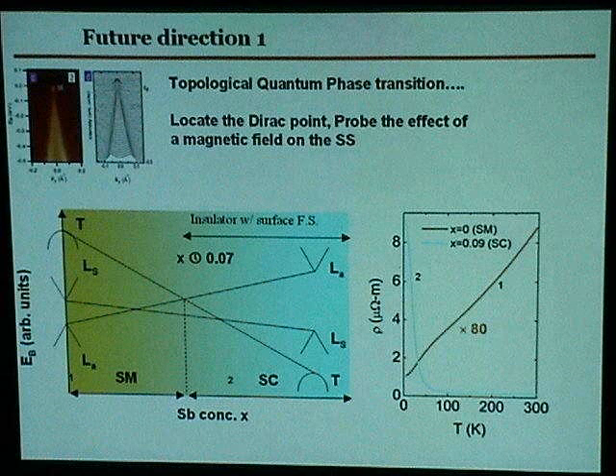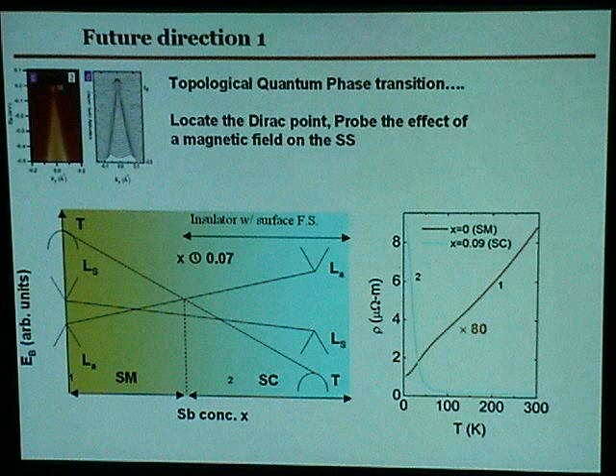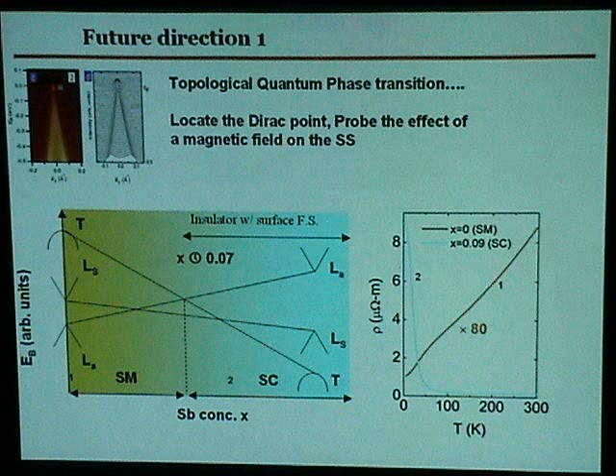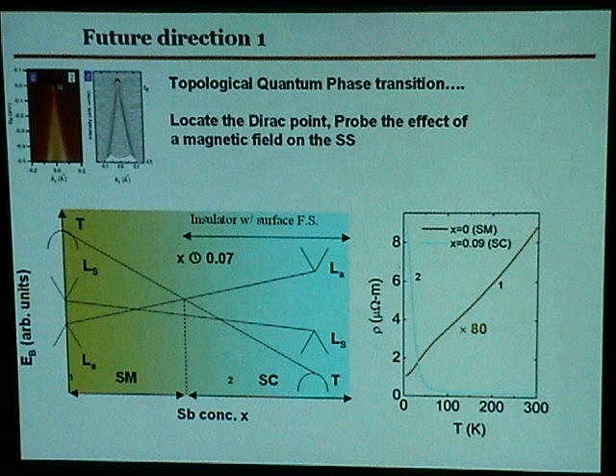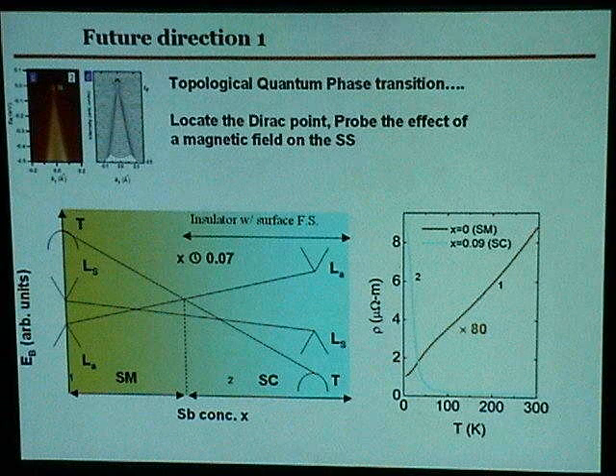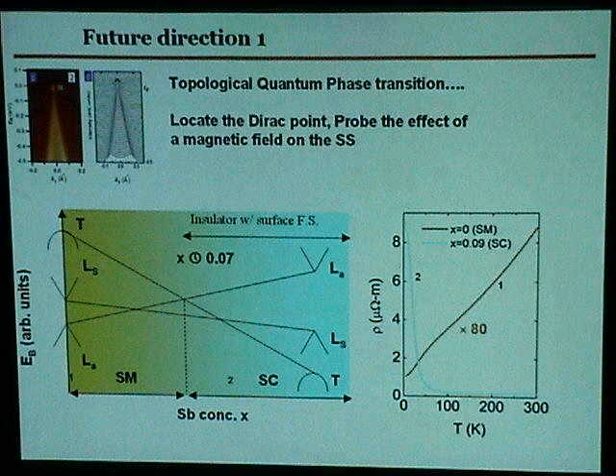You can get rid of other surface state contributions by changing the bulk volume to surface area ratio — just look at the scaling. We are already trying to do this: look at samples and do transport measurements on samples that have different area versus volume, then look for scaling.